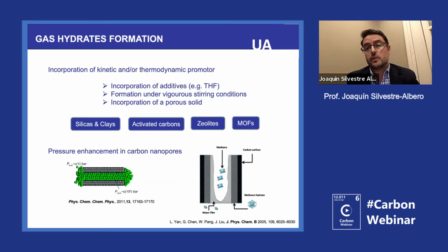So either you can incorporate additives that promote the growth of the hydrates. You can also incorporate agitation, so you can do stirring, and then you can improve the contact between the gas and the liquid. Or the third option is the incorporation of a porous solid. And you can see that in the literature, there are already studies with silicas, clays, activated carbon, zeolites, and MOFs.